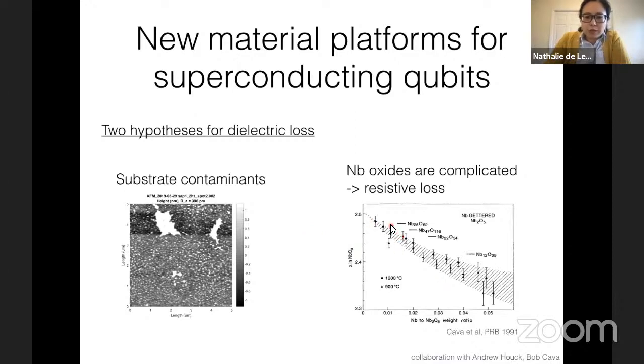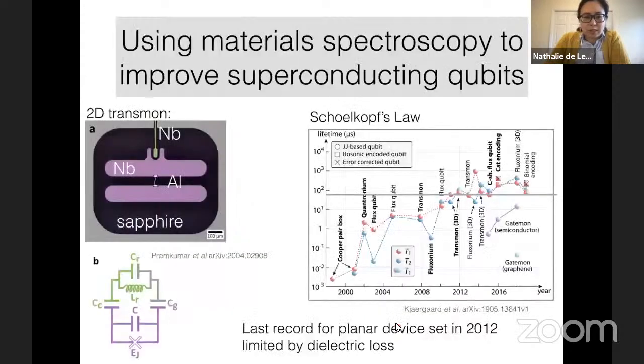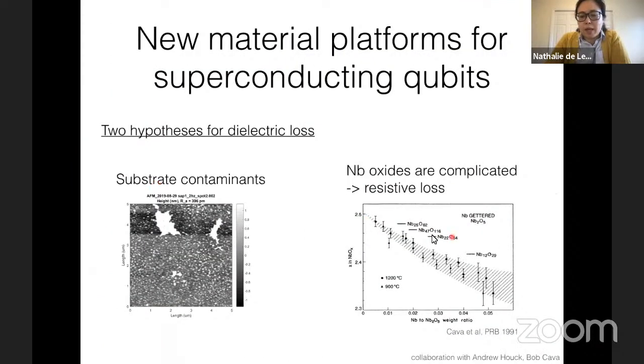The second hypothesis is that IBM and Andrew Houck's group use niobium as the capacitors and resonators that are connected to their aluminum oxide Josephson junction. And Bob pointed out that niobium oxides are incredibly complicated. You can have many different stoichiometries. All of these phases are metallic and kind of poor metals. So this can just lead to straightforward resistive loss that really kills your lifetime.